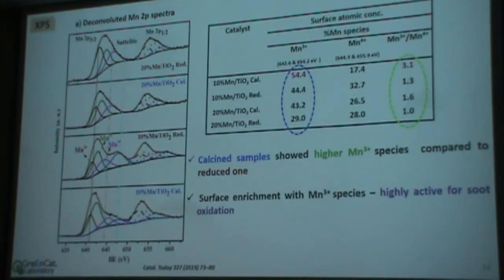And what would be the other reason? Because the oxidation state of Mn plays an important role in the oxidation reaction. As I already mentioned, we deconvoluted the spectra of the 10% and 20% calcined and reduced samples, and we observe that the 10% Mn/TiO2 catalyst contains a higher percentage of Mn3+ species compared to the calcined and reduced 20% samples. That may be acting as the active species for soot oxidation.